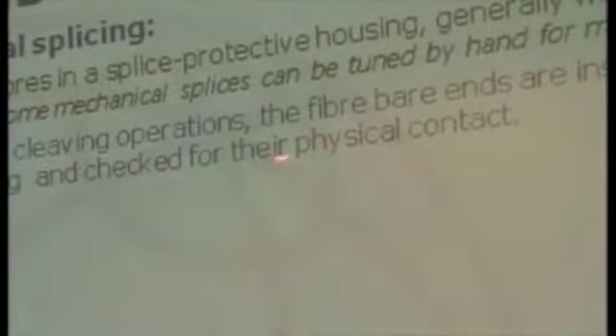Again, we need to strip and cleave the fiber, and the bare fiber ends are inserted in the mechanical housing and checked for their physical contact. For mechanical splice, the proof test is generally not a part of installation because the mechanical structure gives a more sophisticated and stronger protection to the fiber. And sometimes the fiber ends are prepared for splicing by grinding and polishing procedures, especially when this splice is done in the factory.